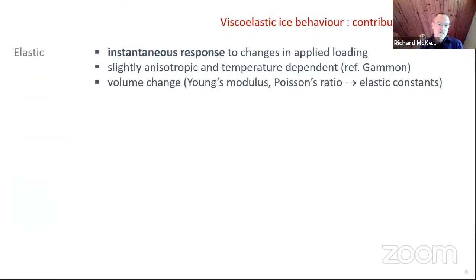In the model we've worked with, we deal with viscoelastic behavior, and there are three main components. There's an instantaneous elastic component, which is slightly anisotropic and temperature dependent. For isotropic ice, any volume changes under loading can be represented using Young's modulus and Poisson's ratio. Whereas for S2 ice, we deal with 4 different elastic constants.